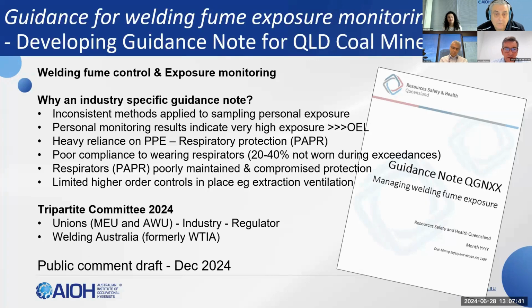We also found that a lot of the respirators being used in the workplace weren't being maintained. There were no structured inspection regimes. And we found quite a lot of the gear out there was being compromised, and we really had no idea what sort of protection wearers were getting. We know what they get when you look at the catalogue and from tests done in laboratories, but really there's not much data to indicate what the protection is like out in the workplace after this gear is being used for a number of months or a number of years.